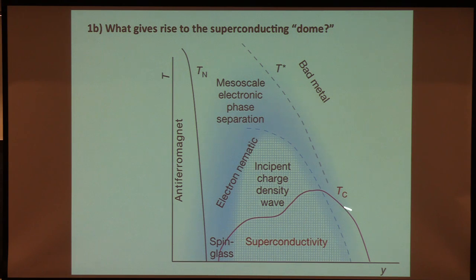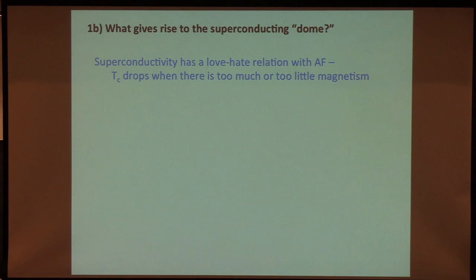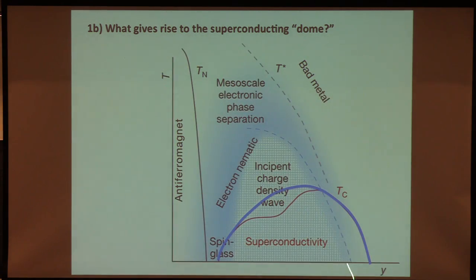Okay, so the second striking thing about the mechanism of superconductivity is you might want to ask, why is there a superconducting dome? Why does Tc rise and then drop over a narrow range of doping? That's one of the striking things that was noticed very early on that's unlike, for instance, lead. If I alloy lead with something, it doesn't really do anything to Tc. So the zeroth order answer to this is also obvious. The superconductivity has some sort of a love-hate relation with antiferromagnetism, just along the lines that we were just discussing. If you have too much antiferromagnetism, it turns the thing into an insulator, and one thing an insulator can't be is a superconductor. But if you get too far away from the antiferromagnetism, you lose this structure of the effective repulsion, and so it wants to be close to the antiferromagnetism, but not too close.